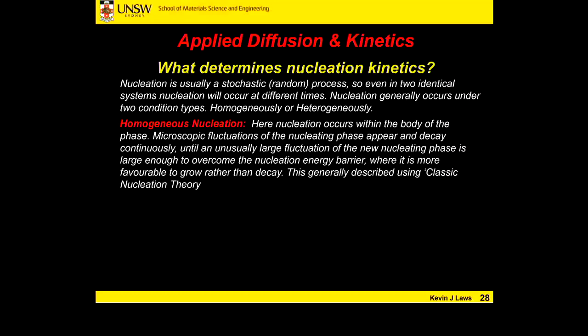All right. So homogeneous nucleation: nucleation occurs within the body of the phase, the material. What happens is we have microscopic fluctuations of the nucleating phase appearing and decaying, in equilibrium. So, for example, going from liquid to solid, randomly in our water we would have crystallites, only a few atoms in size, starting to order, and then they would disappear in disorder. Because if they don't reach a critical size to grow, they have to disappear.